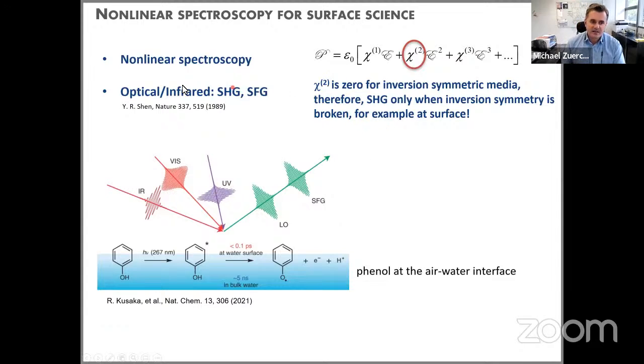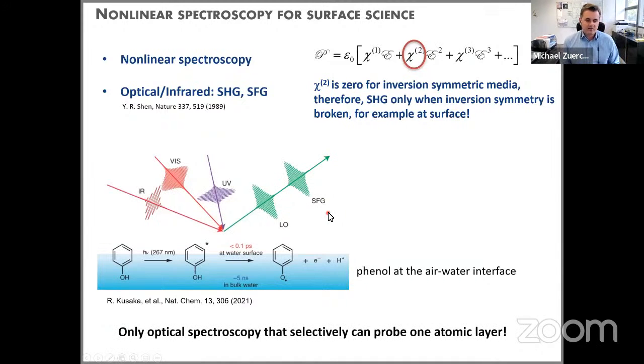This is how these methods got really interesting for studying chemistry at surfaces, especially water-air surfaces with molecules at the interface here. This has been one of the key drivers in that field, using optical and mid-infrared pulses to study properties of molecules at water-air interfaces, using this property that only at the interface, where the symmetry is broken, do these nonlinear components arise. So this is really the only optical spectroscopy with photon in and photon out that can selectively probe one atomic layer.